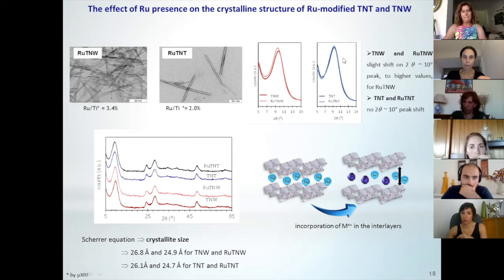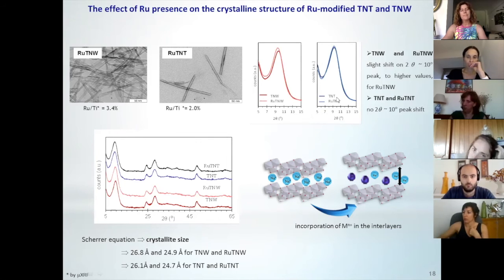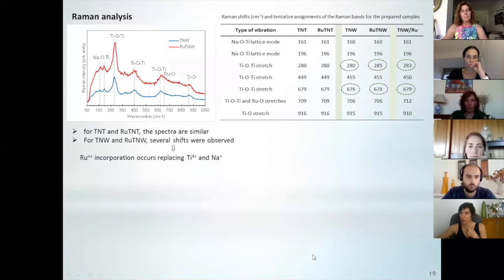We have no news from this point of view, of course, when we look at XRD of titanate nanotubes. This seems to show that we have no changes in the interlayers, okay? So we are not expecting to have ruthenium in the interlayers for the titanate nanotube samples. But we need to know more about this metal, so we decided to analyze the samples by Raman spectroscopy.